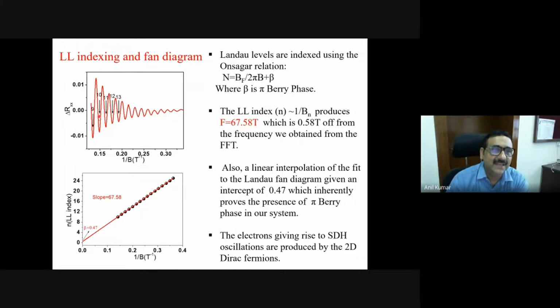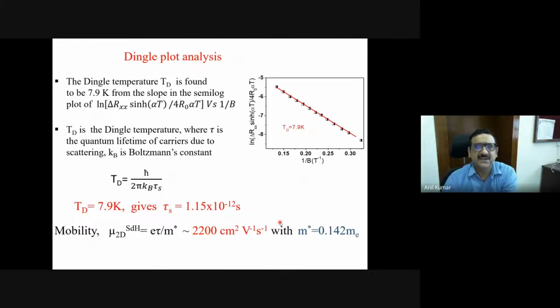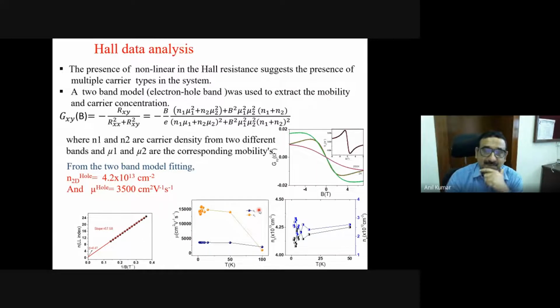And again, we can put this Landau level indexing like 9, 10, 11, 12, 13, and you take this indexing and you extrapolate. Again, it is coming to 0.47. So 0.45, 0.5 is the Berry phase. This is 0.47. So it is again showing pi Berry phase, and this is the first establishment of 2D Dirac fermions in the system. So a rich variety of properties can be obtained here, and we can also look at the mobility. That is the most important aspect here.